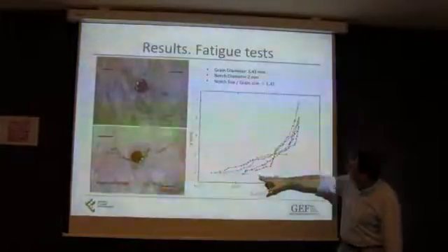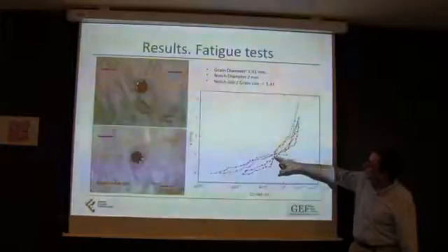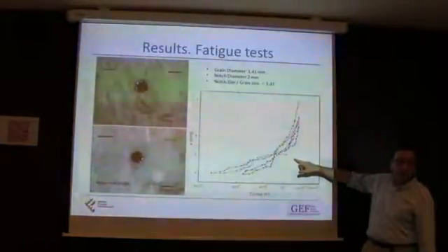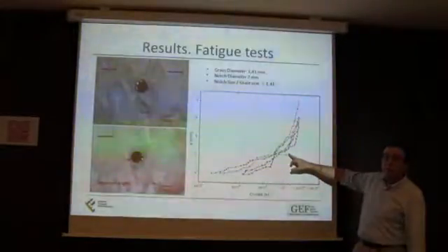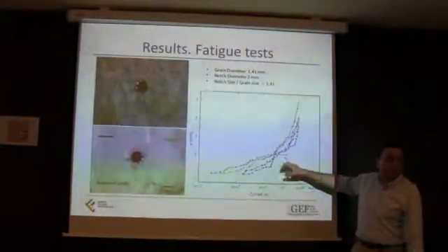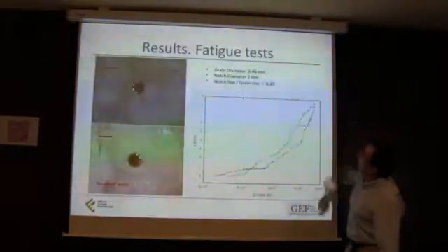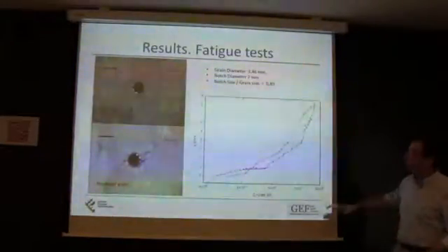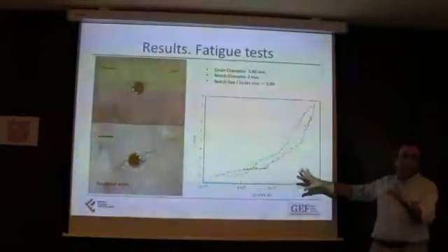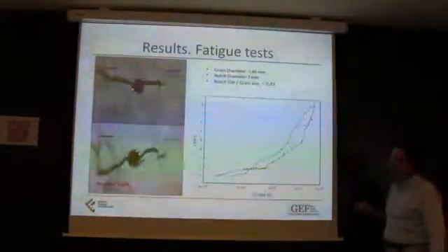And when you represent the crack here, then you start to see this kind of behavior that corresponds to short cracks, right? So we have cracks that are about 3 or 4 millimeters, but still display short crack behavior, obviously. If you go for the last one, now the grain is 3.46 millimeters. By the way, my student Pablo Lorenzino is the one who has done all these experiments, and he has some of the specimens with him.